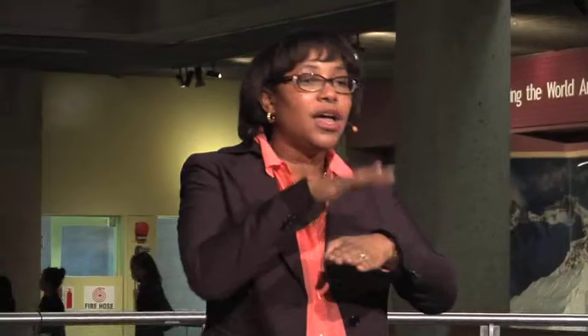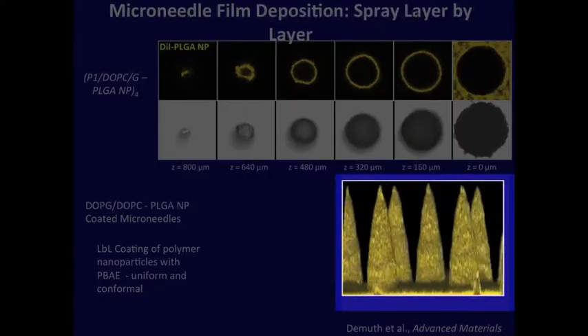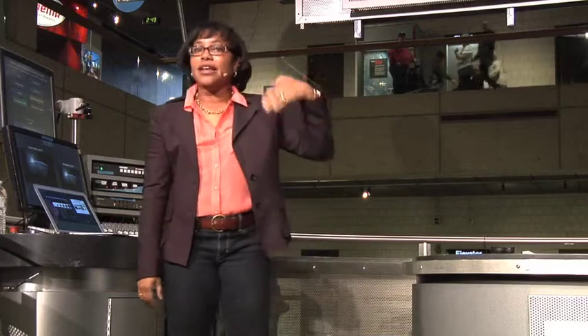You can actually develop microneedles. Those microneedles are so short that they don't get down to the layer where our nerves reside. And so compressing it against your skin, you don't feel anything. It is a degradable plastic that is molded with micron-sized spikes. And on those micron-sized spikes, we're going to apply our layer-by-layer nanofilm. The rotating picture here is actually a confocal microscope image in 3D of what the coated nanolayers look like.